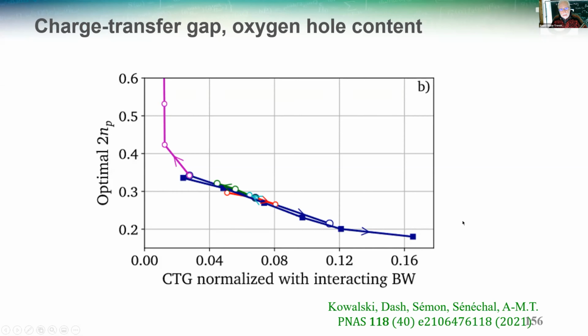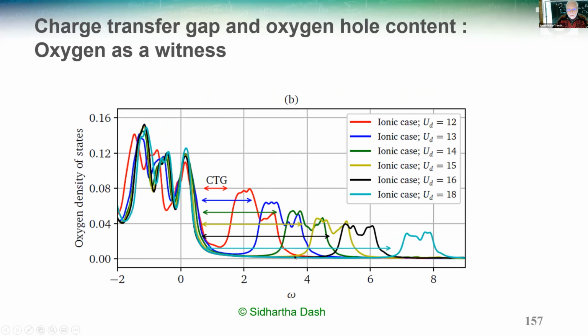Why is it that the oxygen hole content has anything to do with the charge transfer gap? Well, it's relatively easy to understand, it turns out. What is plotted here is the oxygen density of states, or the partial density of states, if you want. It's the density of states projected on oxygen as a function of energy. The Fermi energy here is at 0.